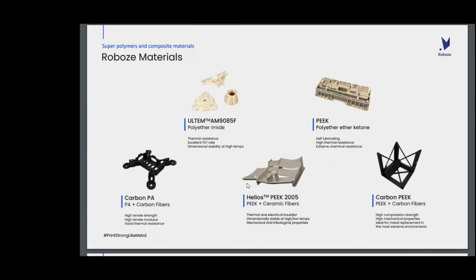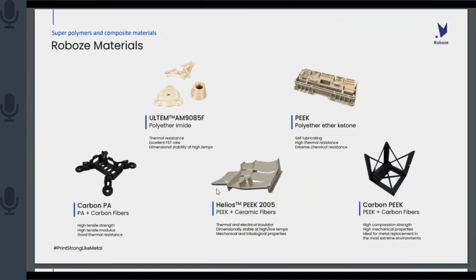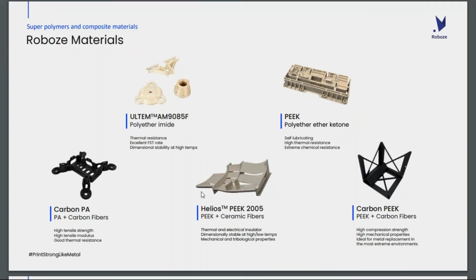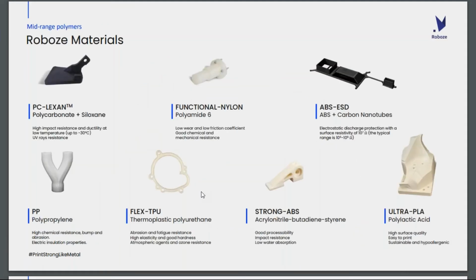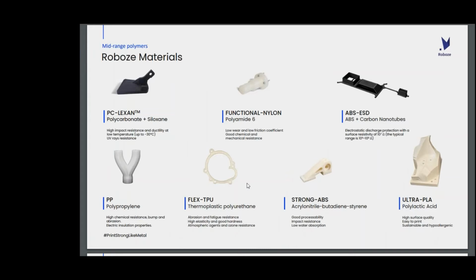So which materials do we have? We have Ultem AM9085F for aerospace, FST rated, FAR 25.853 approved. PEEK, which is our flagship material. This is the most temperamental material, but as well the most performing material in the whole semi-crystalline sphere, until we released the Helios PEEK 2005, which is a ceramic filled PEEK matrix, and we'll talk about it in a second. We have carbon filled PEEK, and we have carbon filled polyamide. Those are the most performing materials we have in our portfolio. But we also have a set of functionalized materials, like for instance, the PC Lexan. This is a polycarbonate with siloxane, with 6 times more impact resistance than any other polycarbonate out there.